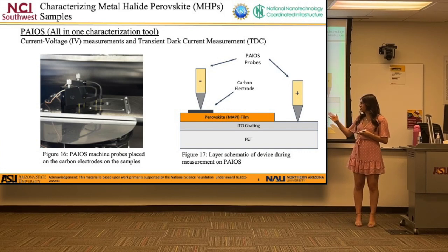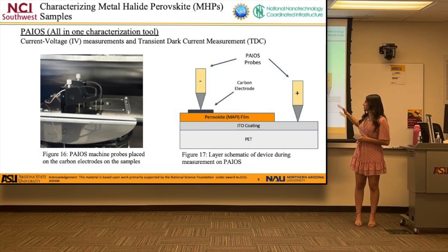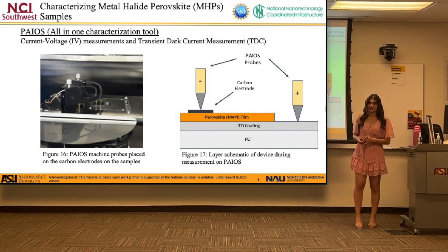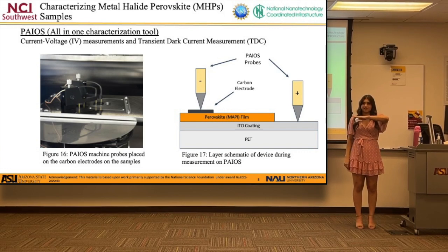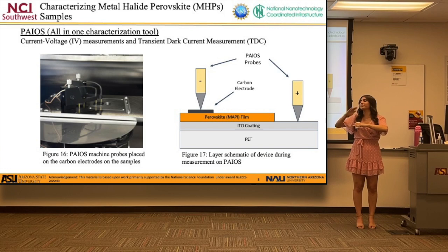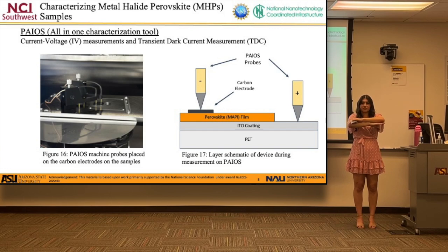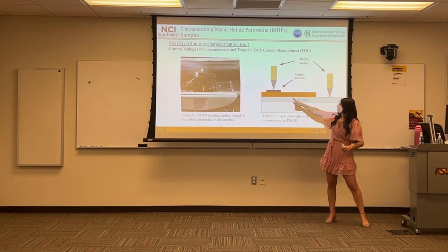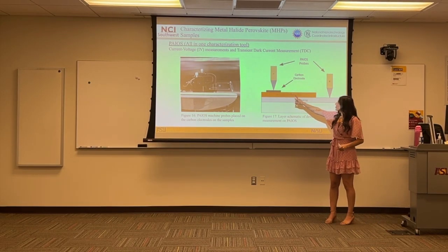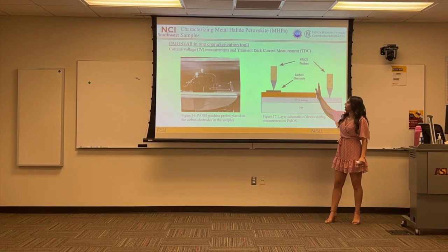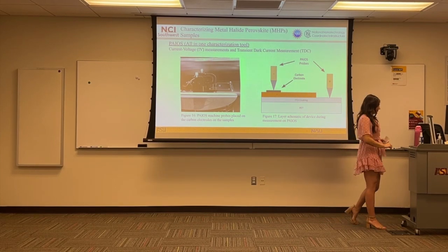loaded into the PAIOS machine, but figure 17 just kind of allows you to physically see what's going on in the process right now. So we have the PET, which is essentially like a flexible plastic, the ITO coating, which is a more conductive coating that comes on the PET from the manufacturer, and then we have the perovskite film, which we deposited during the spin process, and then we have the carbon electrode, which is essentially just a contact point for these 2 PAIOS probes. One of them is negative and one of them is positive.